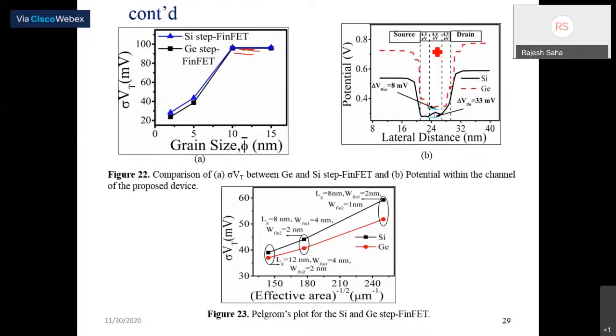As you can see, we divide the channel into three defined sections of three different work functions. Near the source and the drain the work function value is 4.5, and in between, the work function value is 4.4 electron volt. The variation in the potential from the higher to the low work function value is greater in the silicon device compared to the germanium. In case of silicon, it is 33 millivolt. In case of germanium, it is 8 millivolt.